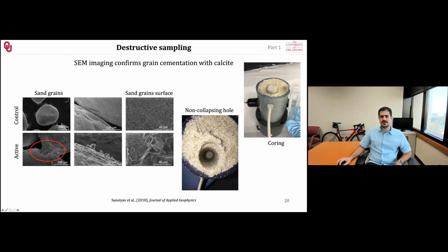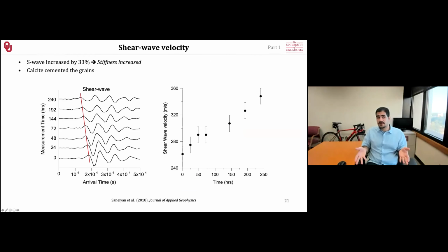And also we were able to see that when we were destroying the sample, basically everything remained intact. So the mini borehole, I would say, that we dug did not collapse on its own because the soil was stabilized in there. Our ground truthing engineering accepted geophysical method showed that the soil stiffness has increased. We saw a 33% increase in the shear wave velocity, meaning that we have actually filled the pores with solid particles, making the shear wave propagate faster. That showed us the calcite actually cemented the grains.